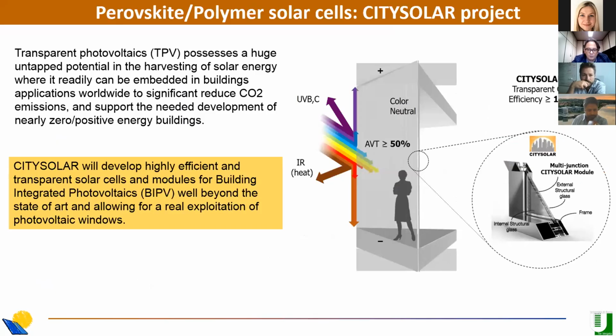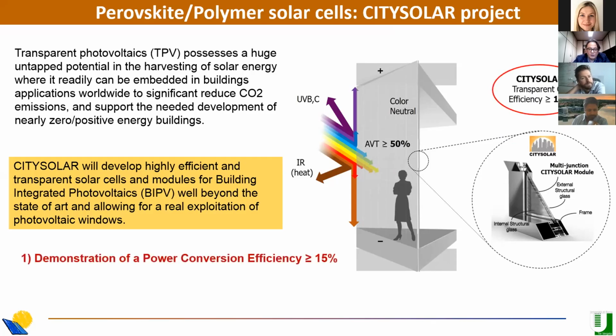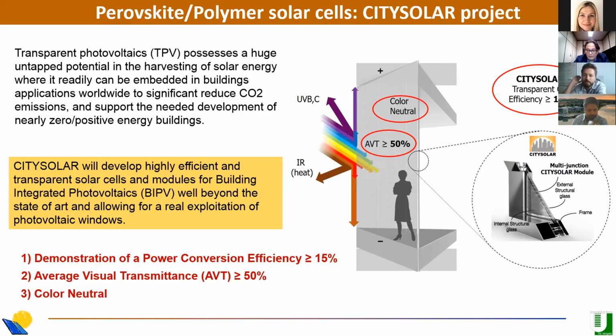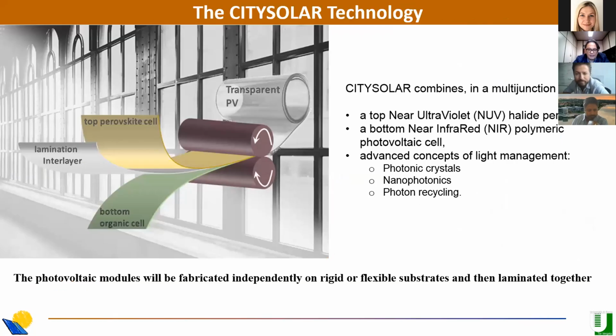However, we found a different way to get even more. And this is the City Solar project. So we find that we can indeed a little bit alleviate or reduce the difficulties of making the tandem solar cell by replacing the organic solar cell with a well-developed strategy of polymeric solar cell. So this is the main goal of the City Solar. City Solar aims to demonstrate a power conversion efficiency larger than 15%, with an average visual transmittance larger than 50%, and with color neutrality, or as close as possible to color neutrality. So the idea is to laminate together a top perovskite solar cell with a bottom organic solar cell, and then to create the City Solar technology.